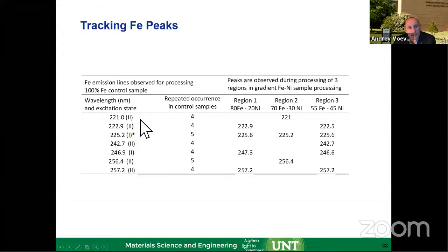When we take in the light during the three regions, near bottom, midway, and finishing up the sample, we have multiple spectra taken, averaging them out. We see, for example, for iron, this characteristic peak, and this is all in the UV region here, 221 nanometers. Now, the numerals here, 2 and 1, are in spectroscopic nomenclature. The 2 means singly ionized, the 1 means neutral atom. After excitation, it goes to ground state and emits that light.